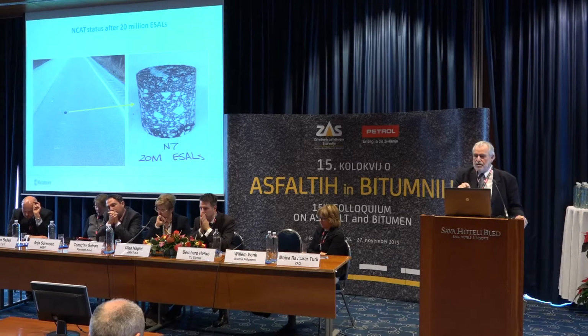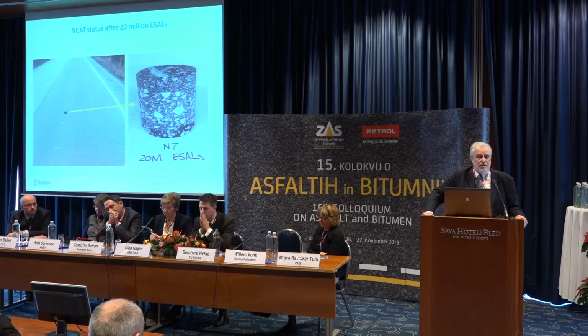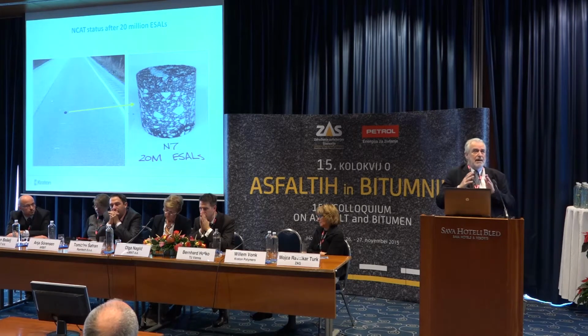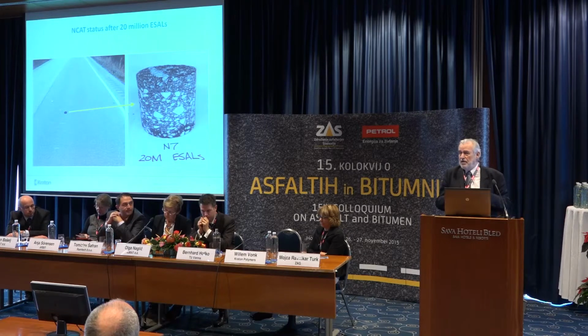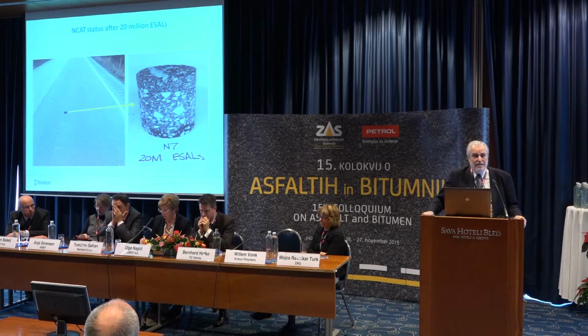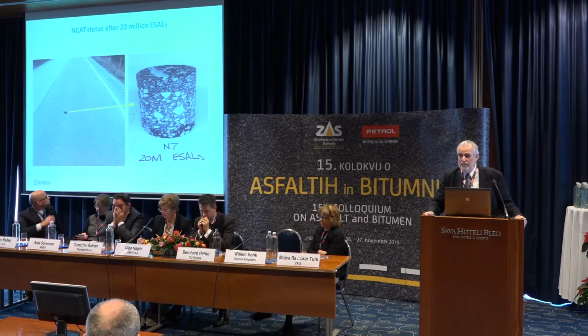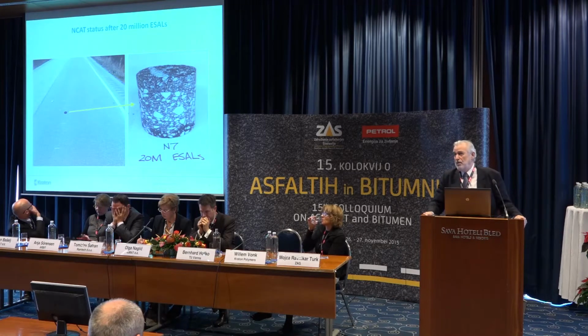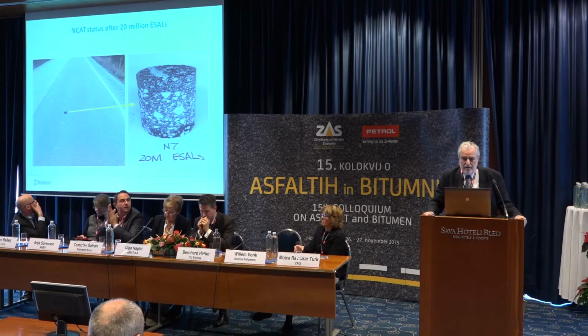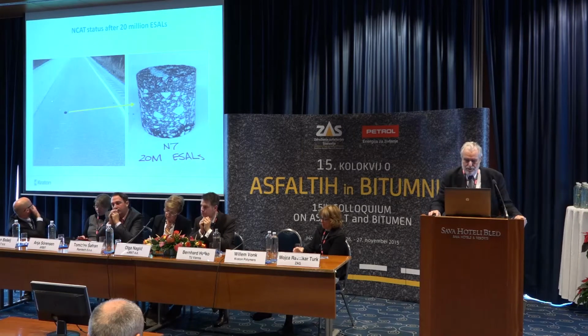This is the status of the highly modified section after 20 million standard axle loads. There were some surface cracks. They took a core, and as you can see on the right-hand side, it is a crack from above, not going very deep. It is anticipated that this section can run for at least another 10 million standard axle loads. However, we will not fund it, because every time we fund this, it is about $400,000. And we believe that we have enough evidence that this works.